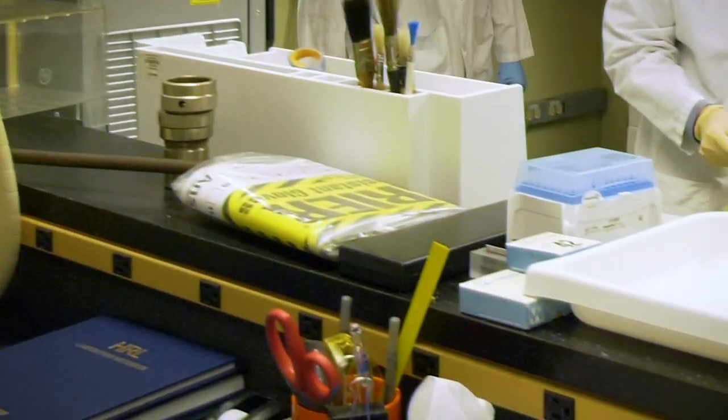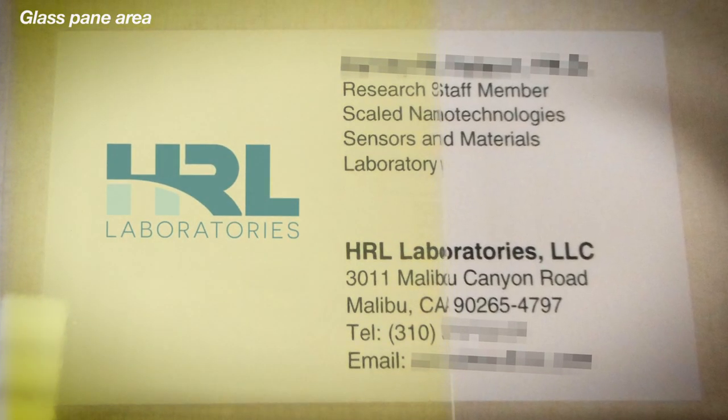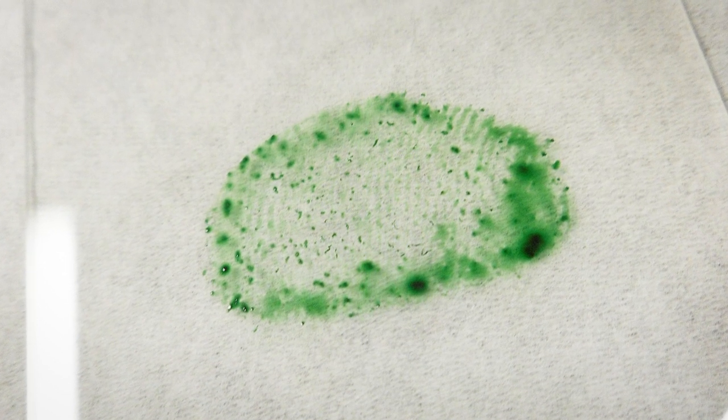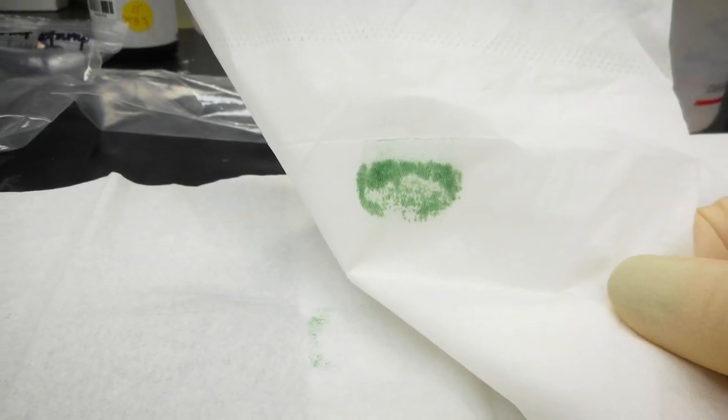That was one of the groundbreaking things we did within our polymeric synthesis — to combine these oil absorbing and oil repelling portions into one coating that has the function of smudge resistance but remains transparent. On top of that, we're also tackling actual smudge resistance two-fold: portions of this coating absorb very small oily contaminants, and other portions help the majority of the oil pool into bigger portions, which makes it really easy to clean.